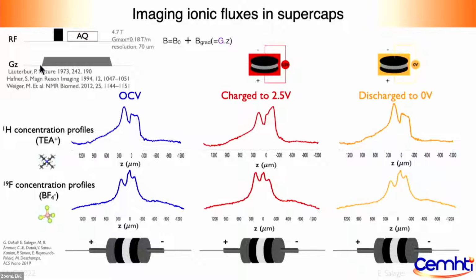imaging. So this time you run the gradient up, you give a short pulse to excite as broad as possible, and you acquire under the gradient. So that's frequency encoding. Now your field is proportional to the position along Z, and you can translate directly your spectrum, the frequency scale here, into a distance, a position scale. So there is some blurring, and Michael Garr would explain that really well in his lecture. There is some blurring related to the chemical shifts, and in our case, this is about 70 micron blurring. But our electrodes are bigger than that.